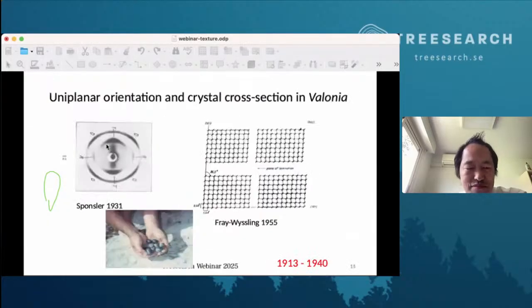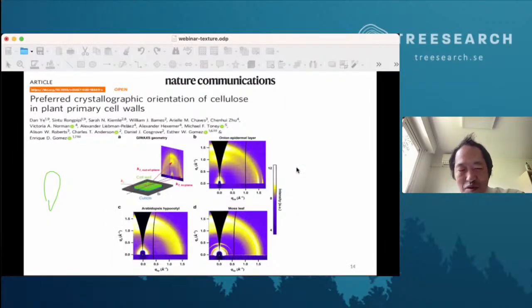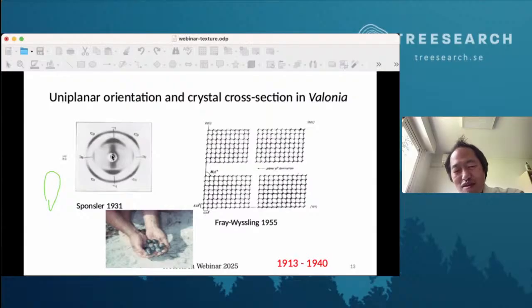so you have strong spots in a diagonal region, which corresponds to the about 4 angstrom spacing, which corresponds to the spacing between the parallel rings, and then you have one corresponding to the 6 angstrom and 5.4 angstrom. So this pattern corresponds to this arrangement, and also another one in the opposite direction, the mirror image of this, which shows that in this